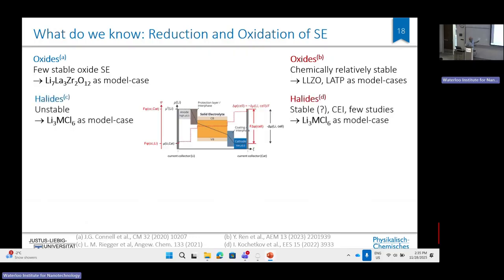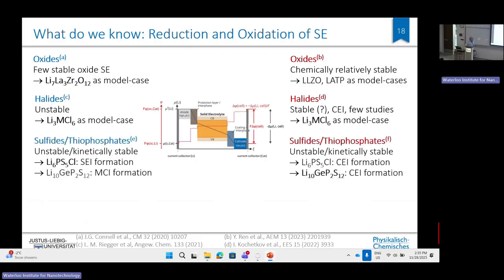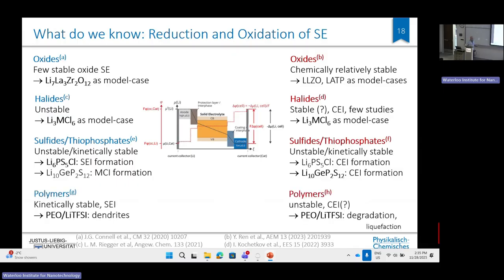The halides or oxyhalides are mostly unstable versus lithium because the metal ions are being reduced. I had a discussion with Linda on that point here, and we probably have to look a bit deeper into some of these materials, but most of these materials are probably not stable at the negative side. The sulfides and thiophosphates are all thermodynamically unstable, but they may form nice, kinetically stable SEIs. Not all, so this is case by case. And polymers, I would say, it depends on the polymer whether they are really stable. If they are stable, then they're probably kinetically stable. They form an SEI, but this is definitely not my piece of cake. They may also have issues with dendrite formation if you go to high rates. Let's exclude polymers here. This is a bit beyond my expertise.